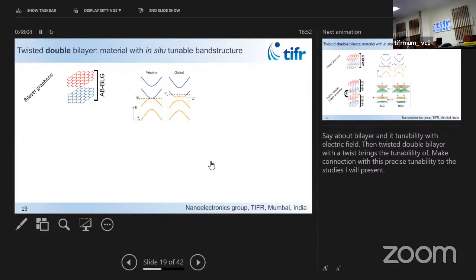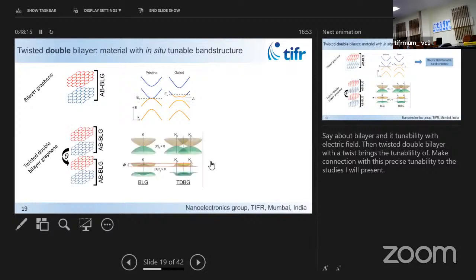The reason is that its band structure is tunable. This system gets around this idea of twisting to a particular angle because you have another knob, electric field, to tune its properties. So the first kind of structure that we can make out of it is twisted bilayer. The mother material is bilayer, you twist relative to each other, and you get similar flat bands, but an additional functionality is there: if you apply electric field, you can vary the bandwidth of this system up and down by applying just the electric field. In the same device, you can tune the bandwidth.